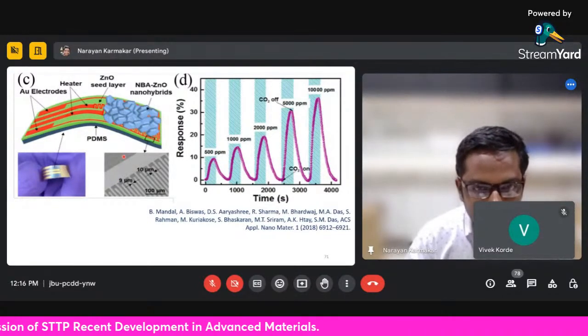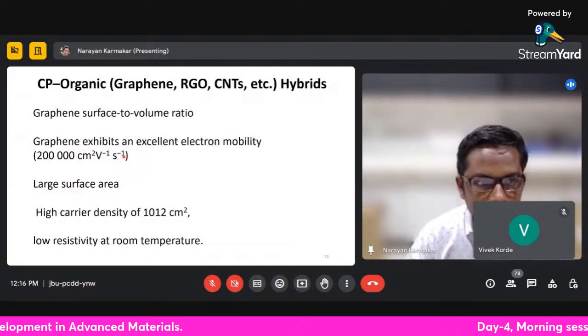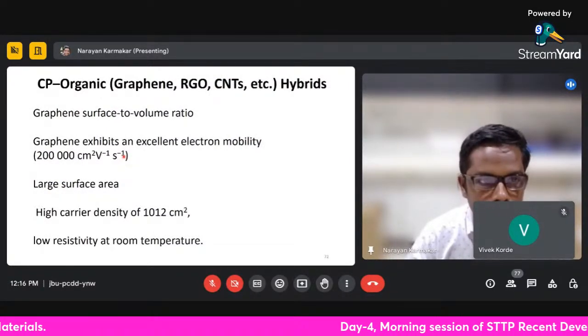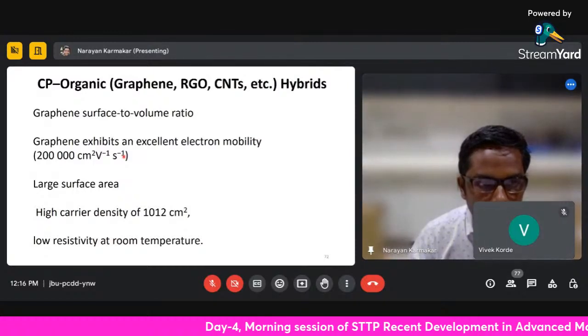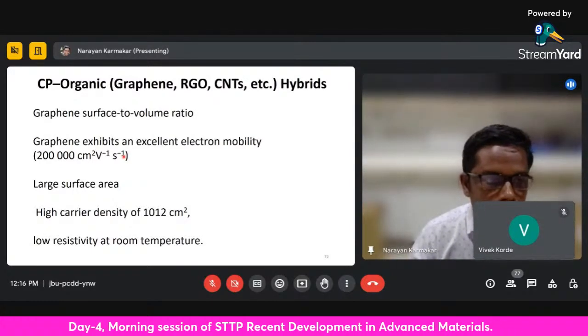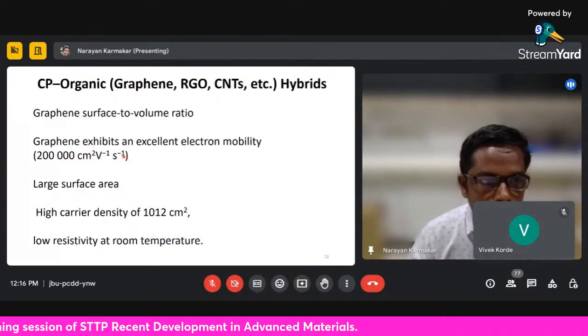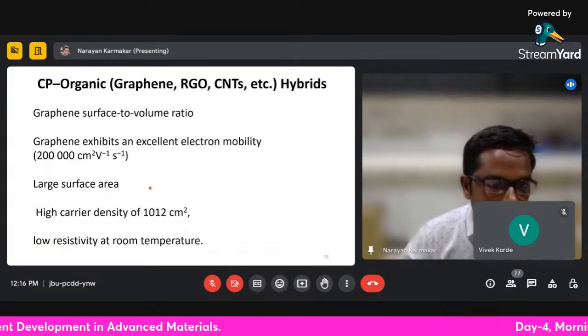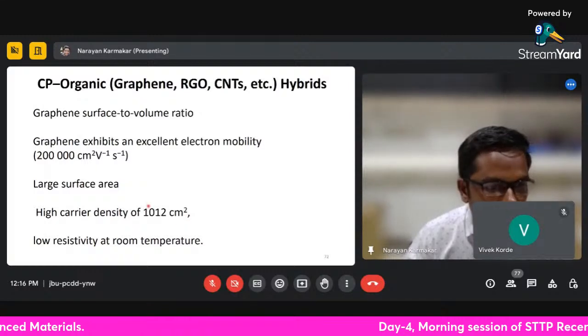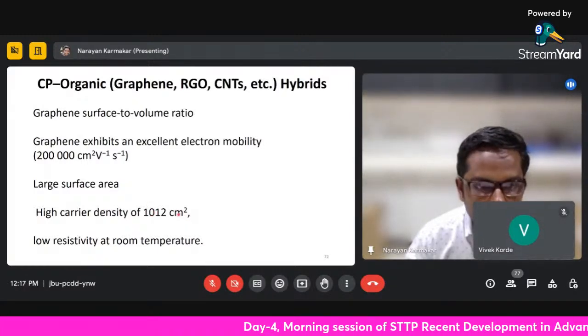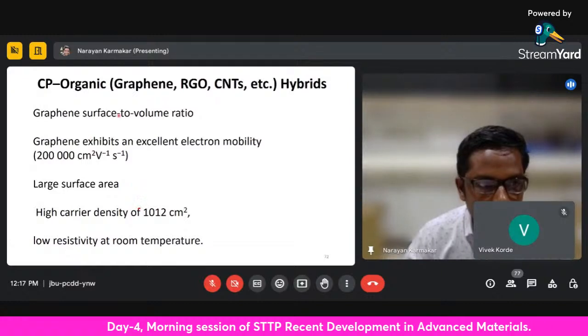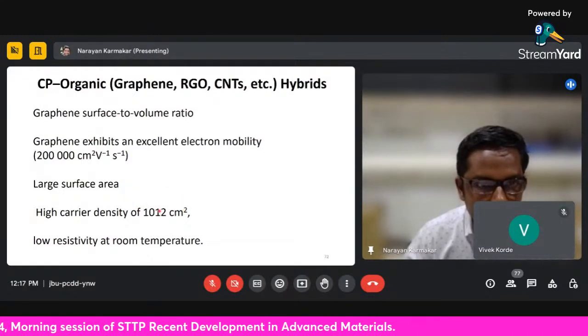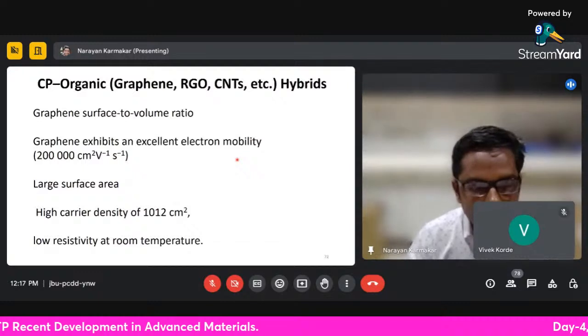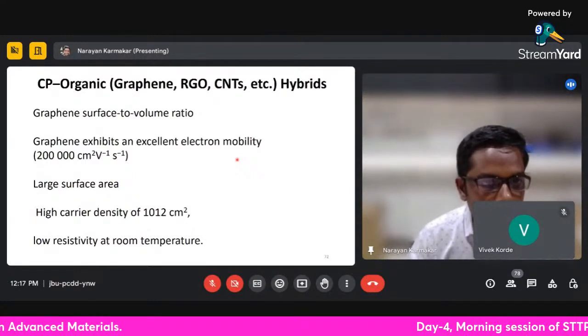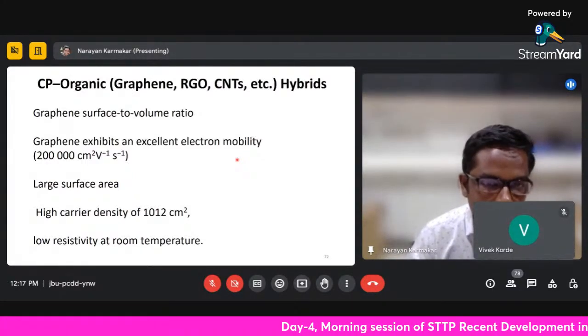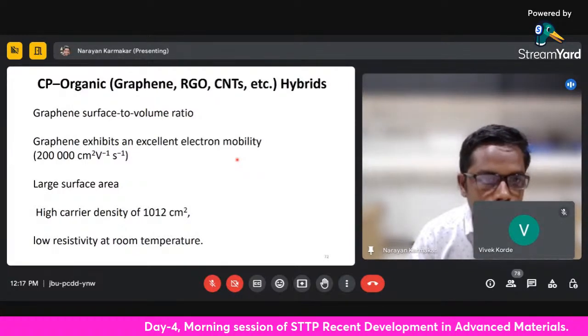Other people are working on nanocomposites, a hybrid nanocomposite based upon graphene and conducting polymer, mainly because graphene has a high surface to volume ratio, and exhibits excellent electron mobility, larger surface area, high carrier density, and low resistivity at room temperature. Because of all this, they make use of graphene-CNT nanocomposites for detection. I don't have expertise in the synthesis of graphene or carbon nanotubes, but this is an upcoming field where people make use of this nanocomposite for detection of various gases.